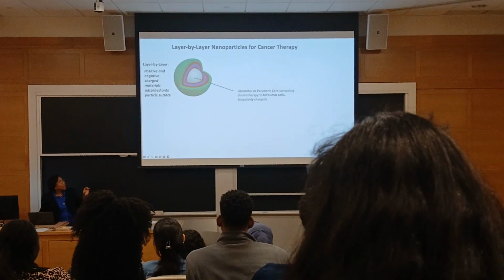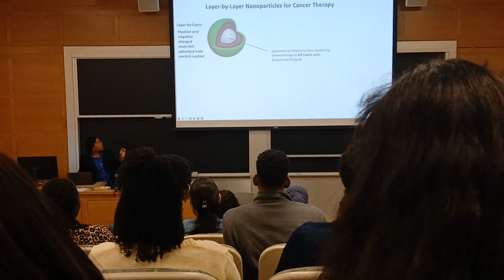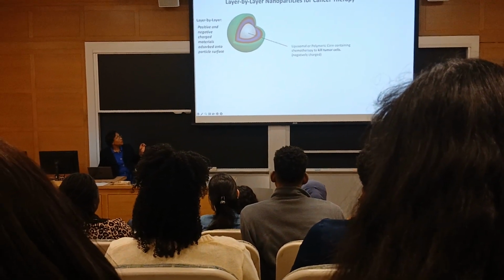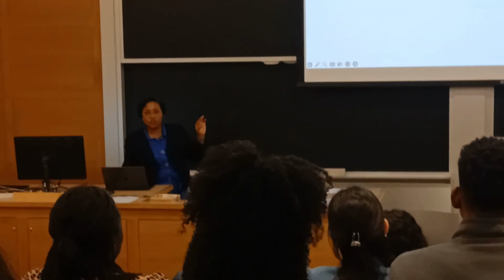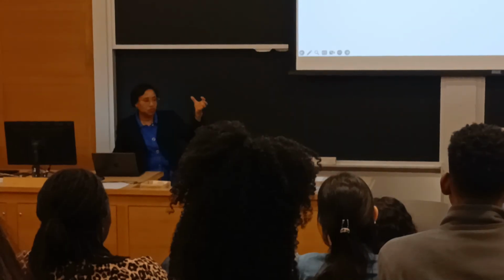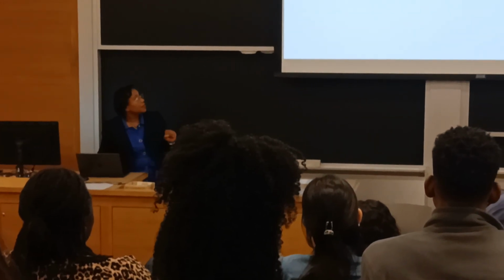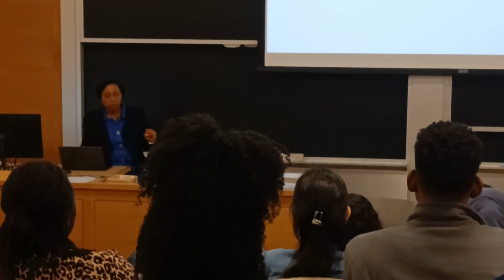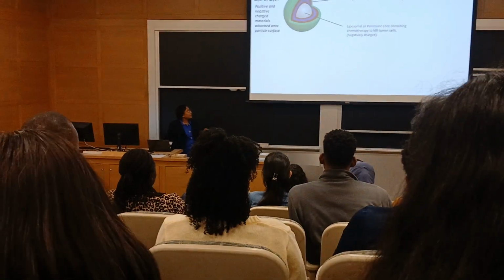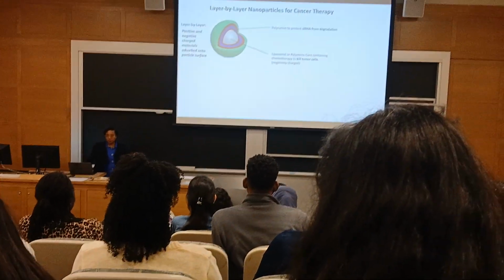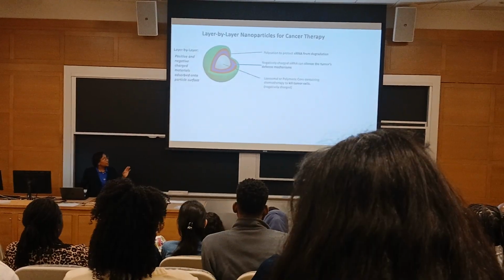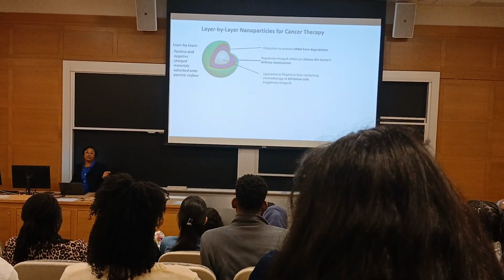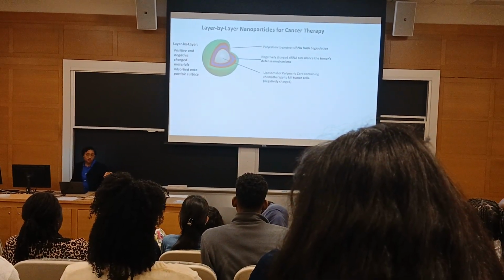So in our earliest work, we began looking at how we might be able to take a liposome and stuff a chemotherapy drug in the core of it. If we design that liposome so that it is negatively charged by introducing some negatively charged lipids into the liposomal layer, then we can absorb a positively charged polymer on top of it. And we can follow that positively charged monolayer with siRNA or DNA or some other nucleic acid. All nucleic acids are negatively charged.